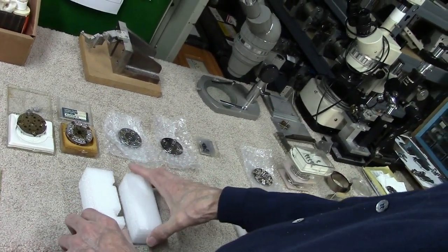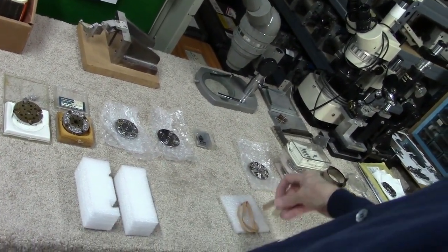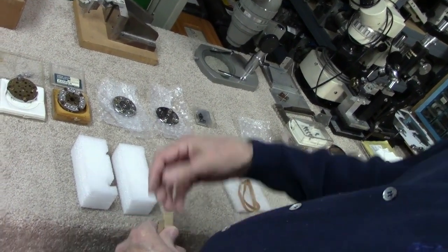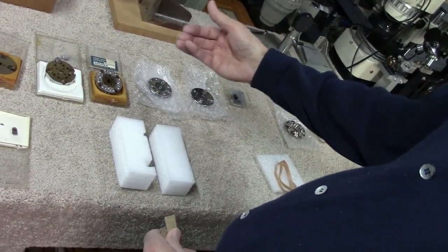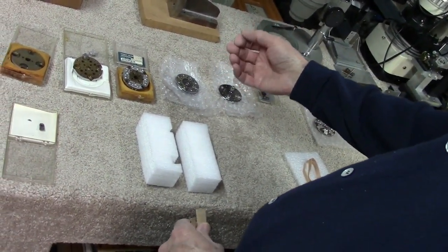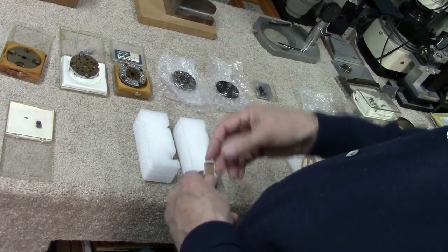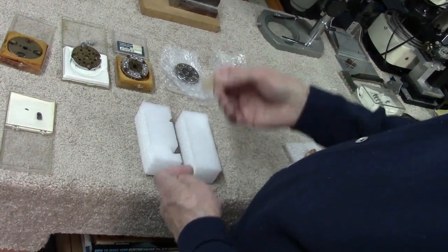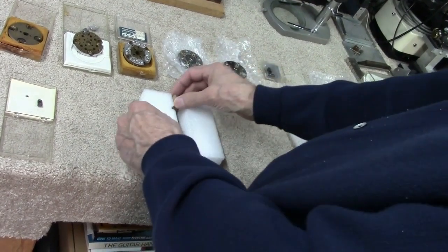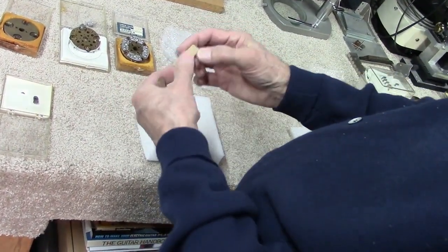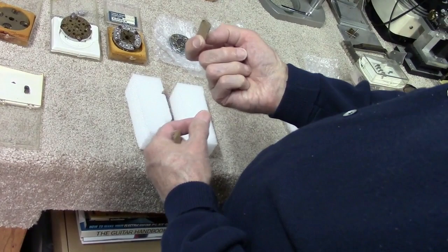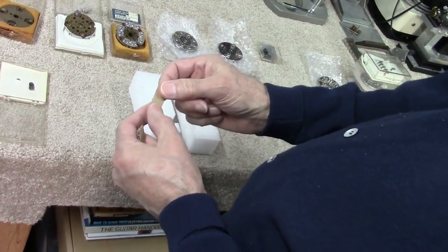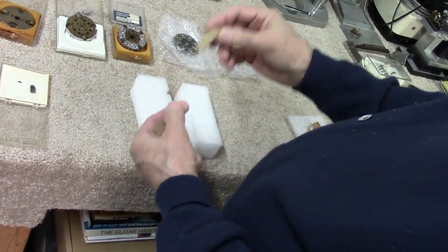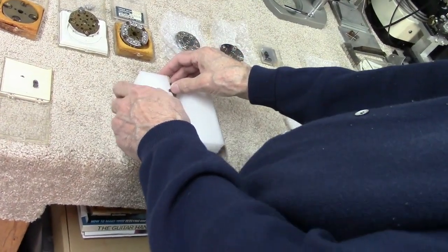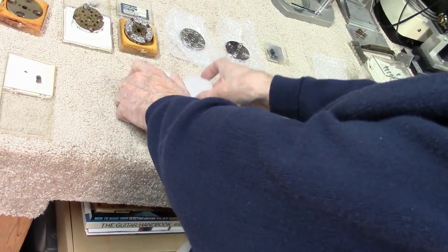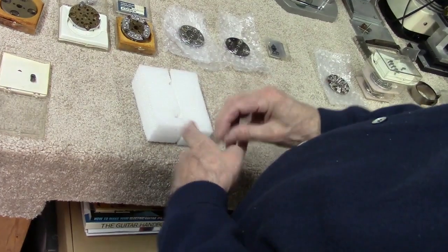So we take the two bonding blocks, and if we're using the early method of capillary bonding with glass rods, then we would need to separate these with some shims of about 50 micro inches thickness. So then we would have our shims here and here.